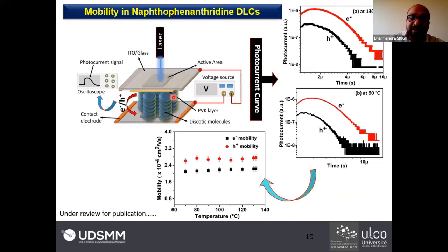When we coat this interfacial layer, many trap states are formed, and under this condition, we do not receive a non-dispersive photocurrent curve. We always receive a dispersive photocurrent curve. In dispersive photocurrent curves, it is hard to estimate the transit time. So we developed a program to do the fitting, and that exactly tells where the transit time is, with a percentage error of 1%. We found that this compound shows ambipolar charge transport with electron and hole, in which hole mobility was slightly higher as compared to the electron mobility. These details are communicated for publication.